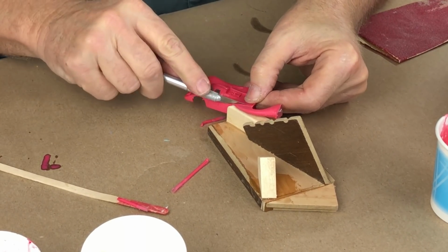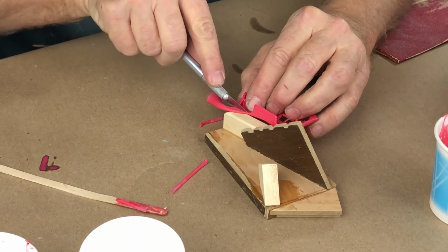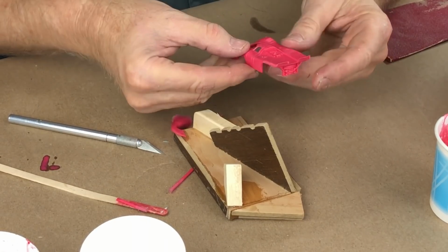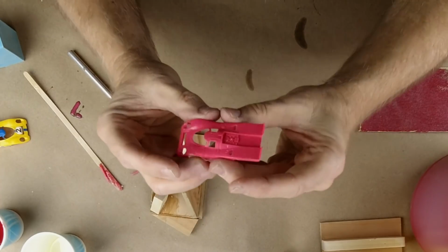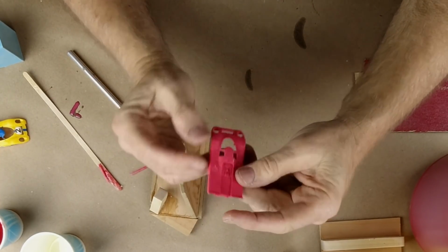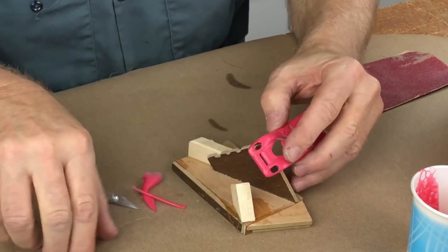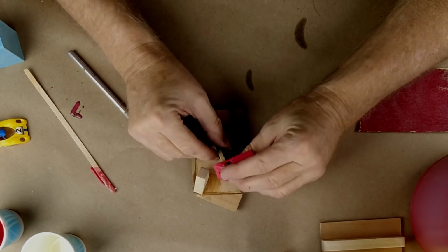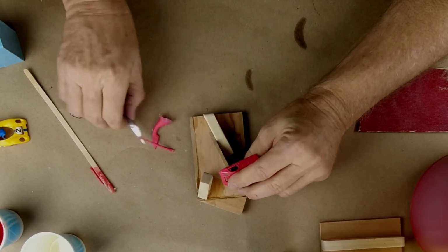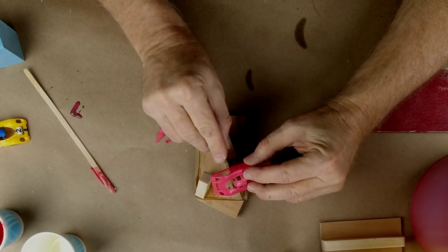See, now normally this resin would be soft enough that I would just cut it with a knife. Very quick and easy. There we go. Okay, so that will need to be finished. All right, so we're a little warped, but hey, look at that. Wow, look at the detail. Not a bubble in sight. Spoilers are complete. Let's get this wheel well out of here. See this little wheel well? That was essential to keep that from catching a bubble right there. I would have caught a bubble right here if it hadn't been for this little vent. Same with over here.